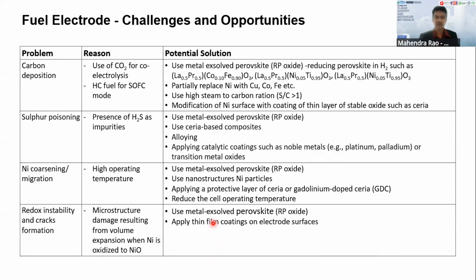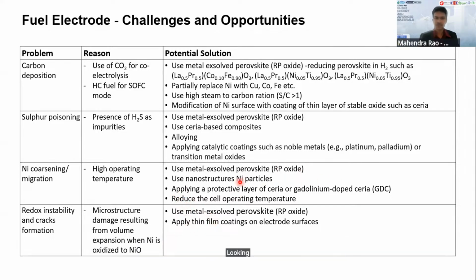So we know solid oxide fuel cell and electrolyzer normally operate at high temperature. So we have some nickel coarsening effect. This is very common for the nickel-based electrode. Again, for some solutions people are looking at the perovskite-based material. Okay, so however, the challenge here is the high electronic conductivity for this type of materials, and then they should try to use the nanostructured materials, and then apply a protective layer such as GDC and reduce the operating temperature. So these are some of the potential solutions for the fuel electrode.